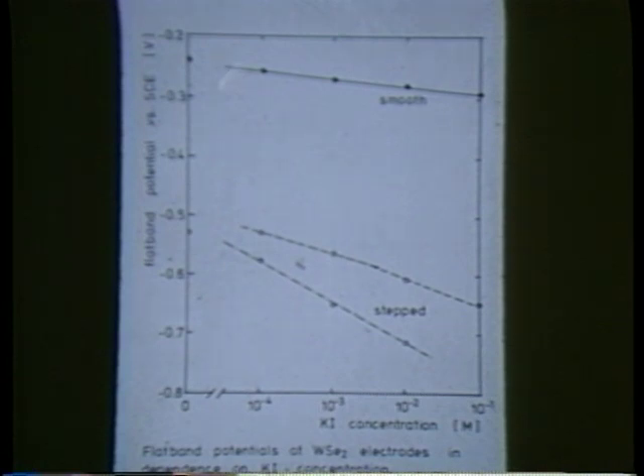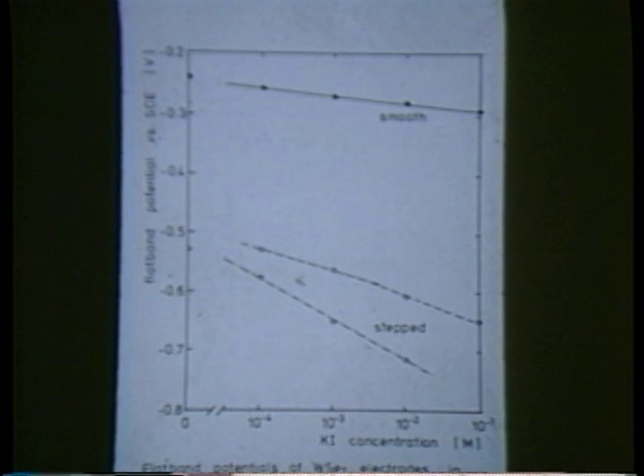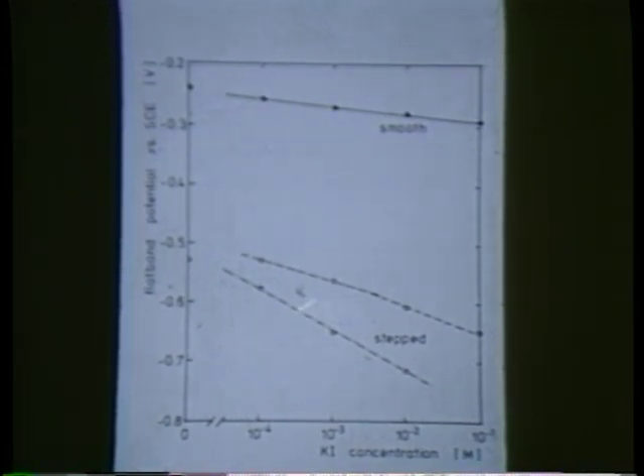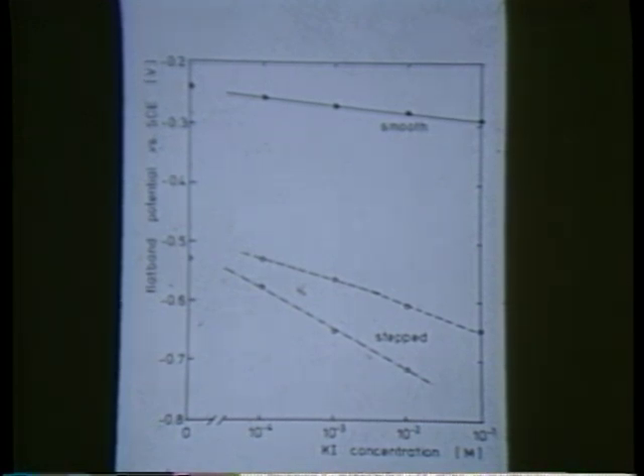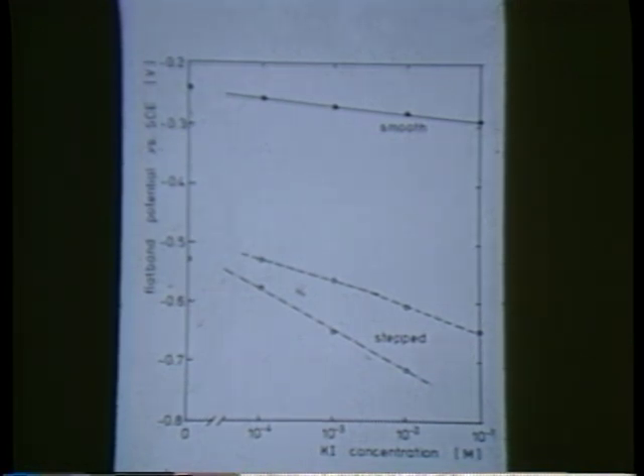in the solid. And you see, in a smooth surface, iodine is such an ion. On a smooth surface, there is very little variation of the flat band potential and zero charge potential. However, if we have stepped surfaces or highly corroded surfaces, then there is a very strong situation and a large shift in the negative direction, indicating that we have now a great deal of iodine ions adsorbed on the surface, increasing concentration. And this adsorption obviously occurs on such specific surface sites where these d orbitals of the transition metal can interact with this iodide.